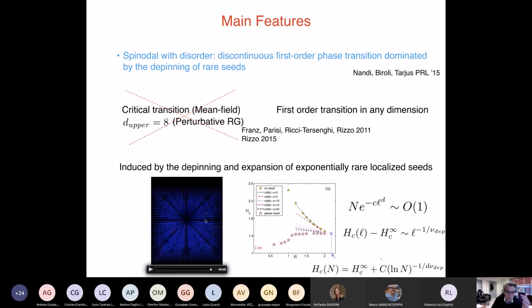But also the bigger the droplet, the rarer the droplet. So what we can understand is that, in the thermodynamic limit, this spinodal transition is driven by extremely large droplets, which are super rare, and the value of the field at which the spinodal transition takes place is the value at which the boundary of this droplet is able to depin, meaning to push and expand away. So you should think of this like a depinning of a random manifold, because the interface of the droplet feels a force: the external field favors energetically the other phase, which means that if the interface increases, you gain in energy. Now the problem is that the interface has trouble increasing because it is pinned by disorder, and this is why it's like depinning.